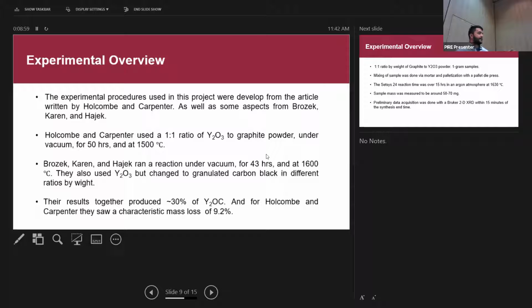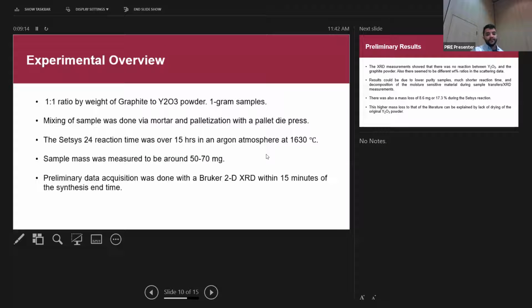And in Holcomb and Carpenter, they actually ran their synthesis in a thermal analyzer like I did, and that's how they got the characteristic mass loss of around 9.2%. So now I'm going to talk about the one that I developed based on these articles, which is the same 1-to-1 ratio, but I used by weight because I was trying to just get acquainted with the instrument and develop the protocol before I actually did the by mole, which uses a lot of yttria.